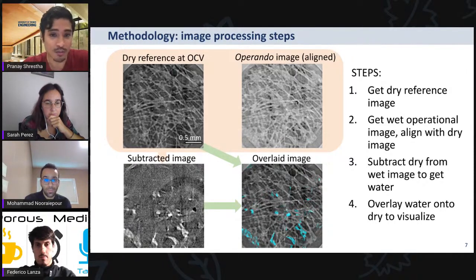When we just look at the operando image, it's hard to tell where the water is and where the fibers are. So we take a subtracted image, which is shown at bottom left, and then we threshold it using methods such as OTSU, and then we overlay it with the dry reference just to contextualize where the water is with respect to the fibers and the pore space.